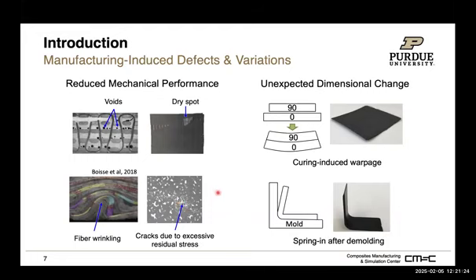So at the structure level, we also see dimensional change, which is very significant for manufacturers, especially for material used in aerospace applications, which requires very tight control on dimensional stability. There are cases where, because of the material anisotropy, we expect to see warpage in the part if we stack two different orientations of the fibers. Or there are cases where we develop what we call spring-in of the part, which means we want to make a 90-degree bracket or flange. If your mold is a perfect 90 degrees, and we drape the fibers and do the infusion and curing, once you do the demolding and measure the enclosed angle, it is no longer 90 degrees.